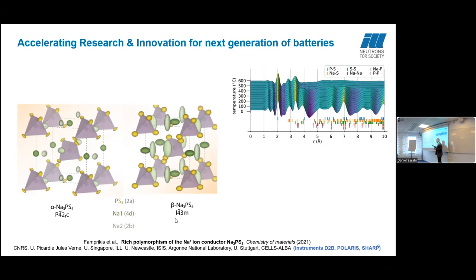And as I saw this, it immediately reminded me of ice VII. I don't know if you know about ice, but there's one particular phase called ice VII, which has a very simple structure. It's disordered. The water molecules inside are disordered. The bond lengths don't make sense in this simple high resolution disordered structure. The bond lengths in ice VII are all too small. But when you look at pair distribution functions, you see that the waters actually aren't distorted. They're real waters. It's just that you see a statistically averaged structure that distorts things. So I think that was kind of cool.